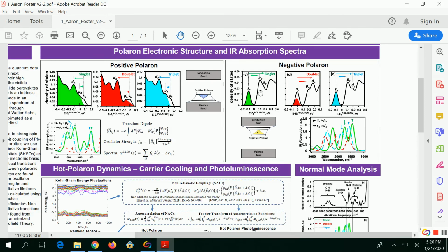I was going to put that on here because last year I got an aggressive reviewer asking why I didn't put any hybrid functional calculations. I was looking at those today. I basically saw that qualitatively the electronic structure is the same. We still see a gap here for this subgap, which we wanted. I think it was a little wider including the hybrid functional. And there are the same characteristic trends with where the peaks were in the states. So in terms of electronic structure, there wasn't that big of a difference for what we're trying to focus on.